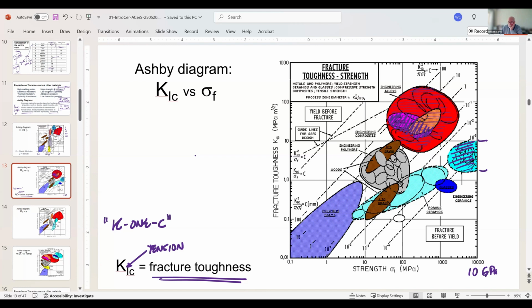Wood tends to be about the same fracture toughness as ceramics. Porous ceramics are down here, with lower fracture toughness. And then you get into your engineered polymers in here, which also have relatively poor fracture toughness and lower strengths. You might say, well, why would you want to use that? Well, we tend to design things to be the maximum strength that we can manage, but the bottom line is that we don't always need that much strength. For example, your polycarbonate in your eyeglasses doesn't have to have particularly high strength, but you would like it to be low mass. So there's a lot of opportunities, and you select the material based on the design that you need.